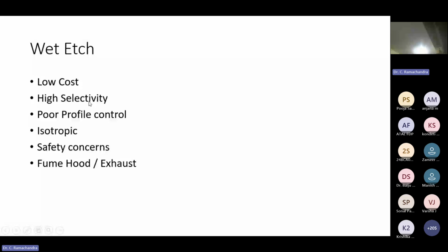The problem is poor profile control. It etches in all the directions. So you cannot have a profile only vertically. Isotropic means it etches in all directions. Therefore, for some applications isotropic is acceptable. Definitely, it is the best thing to go for wet etch because of low cost. Another problem is safety concerns because we are using some dangerous chemicals. We need to be very, very careful. We need to practice all the safety measures.